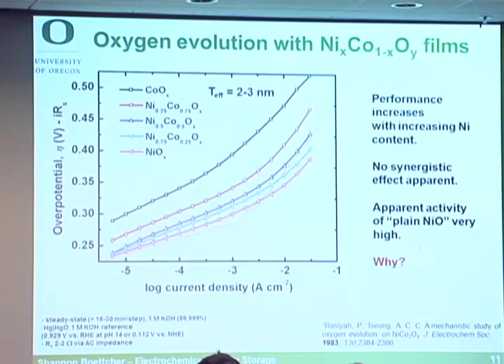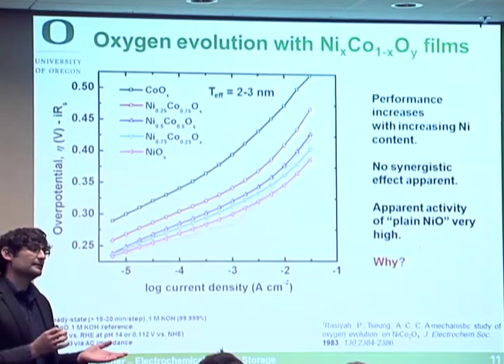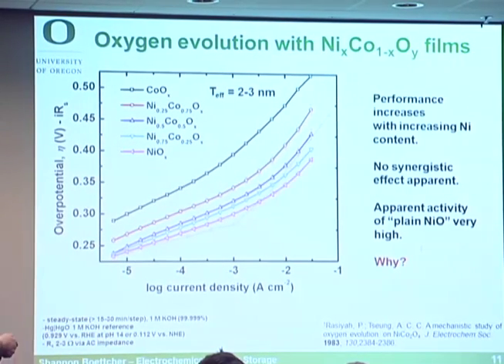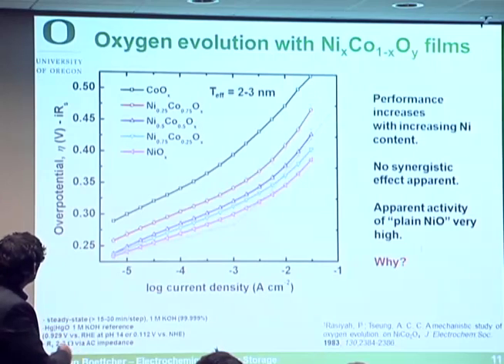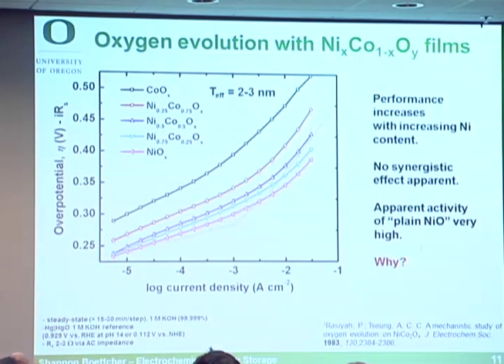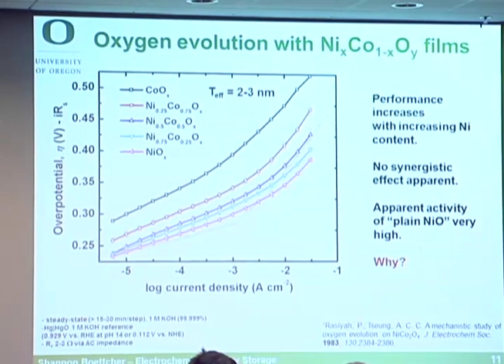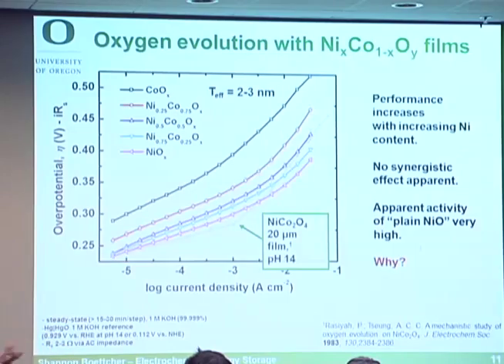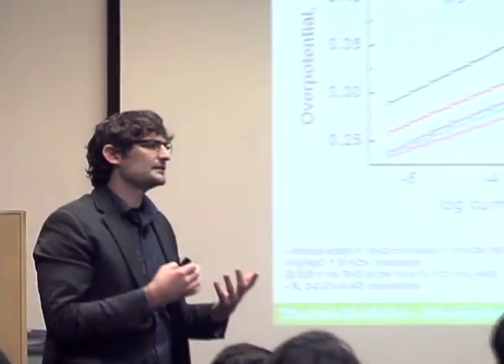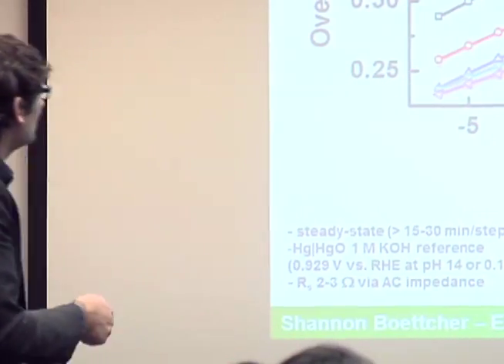There was no synergy. And the other thing that was interesting is the plain nickel oxide electrode we made had much higher activity than we had thought we would see. In fact, if you compare it to the nickel cobalt data from the literature, this nickel cobalt oxide film that was presumably optimized here, and you could get data from many papers, you'd find this very thin film of nickel oxide by itself had performance that was essentially equivalent to this 20 micron thick film of this nickel cobalt oxide. So something was odd here, because the loading's about 1,000-fold less, but the performance was the same. Trying to understand what's going on, certainly wasn't explained by anything we read in these nickel cobalt oxide papers.